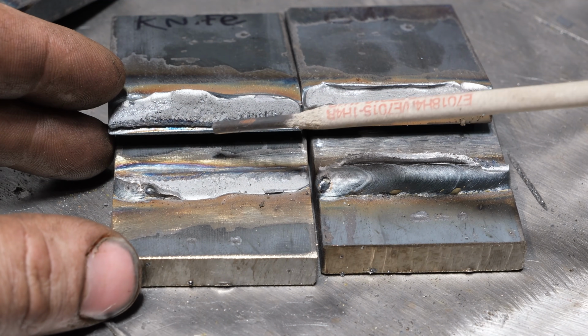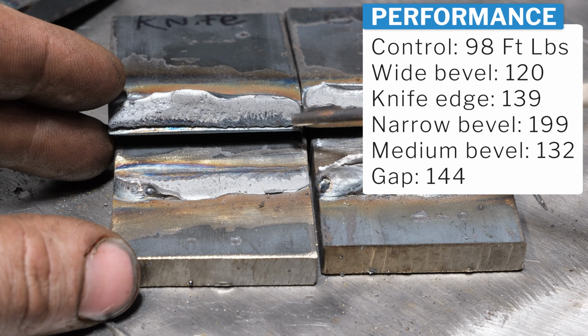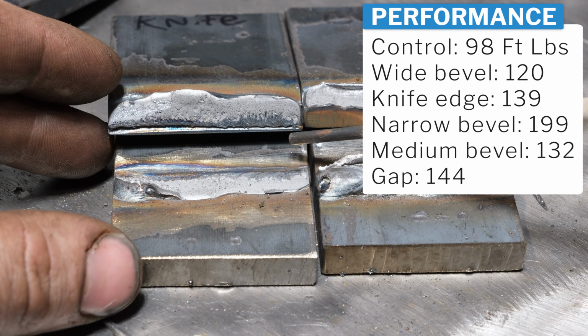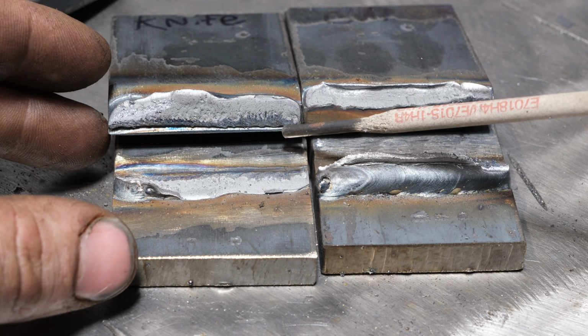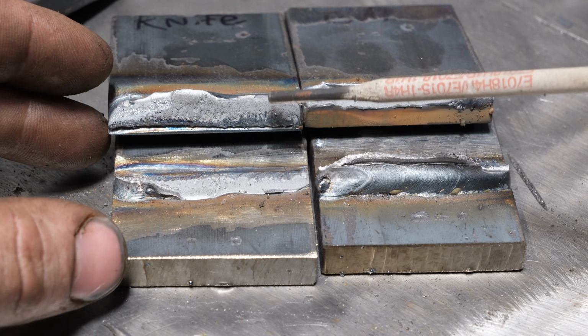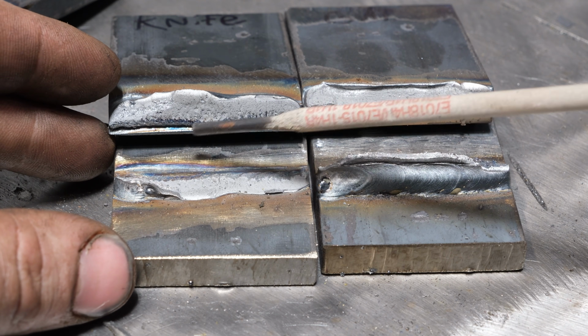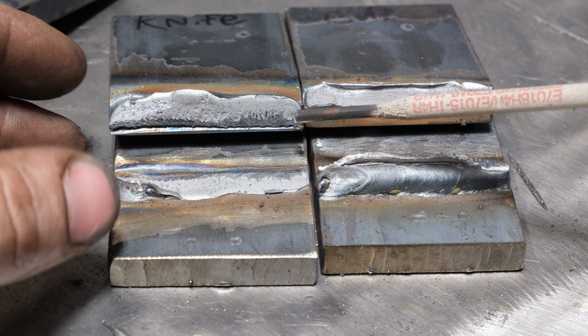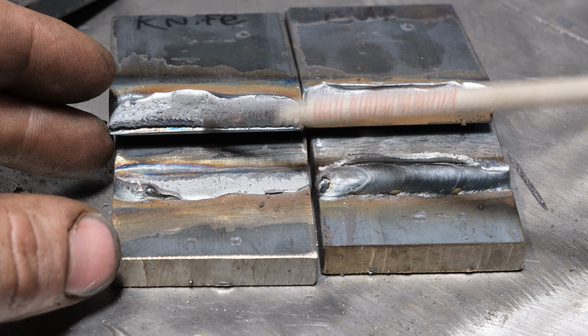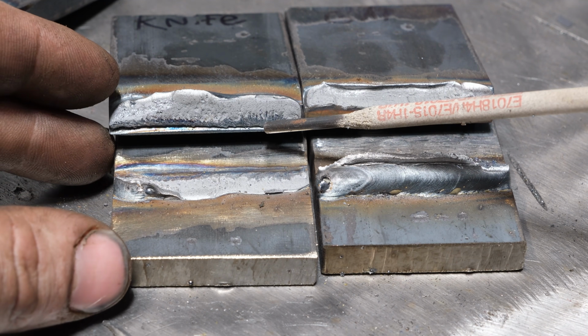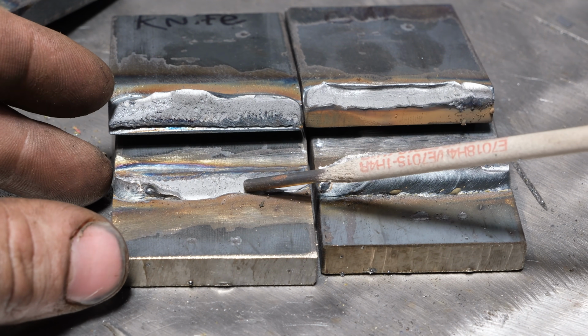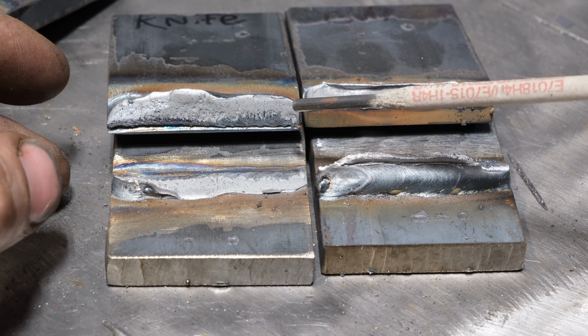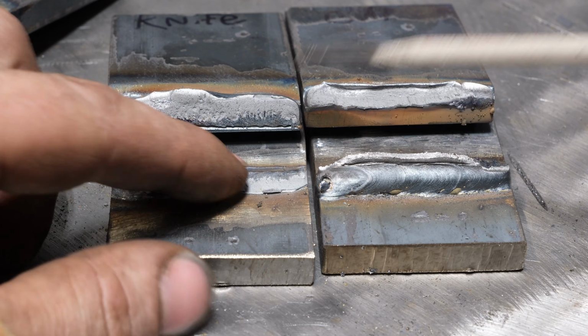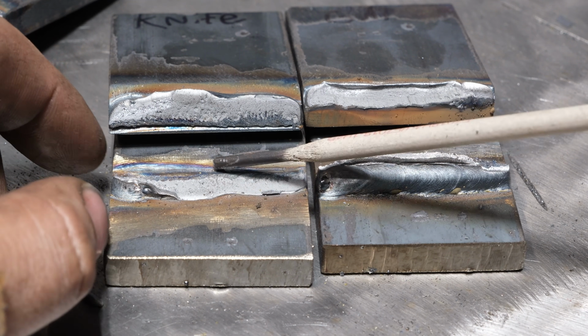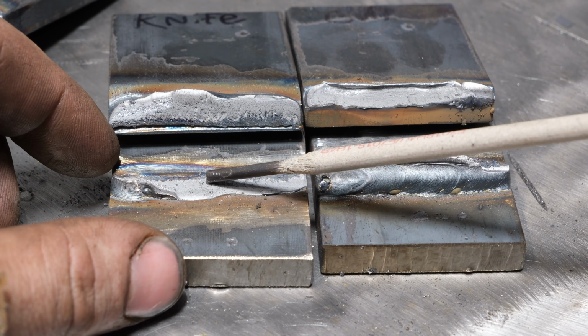So this knife edge bevel did not break down that at all, and that's because we were not running a gap at all. That's the only way you're going to achieve that, and that's one thing we can be certain of on here, is that just running that bevel is not a guarantee of a full fusion weld. You're going to wind up with stuff like this. Now again, it broke more off of the bottom plate than the top plate, and it's not very far penetrated, but it is better than the control by a little bit.